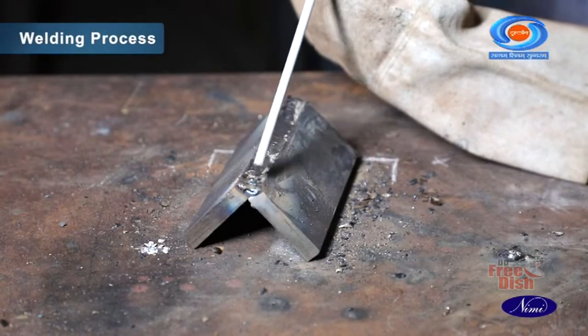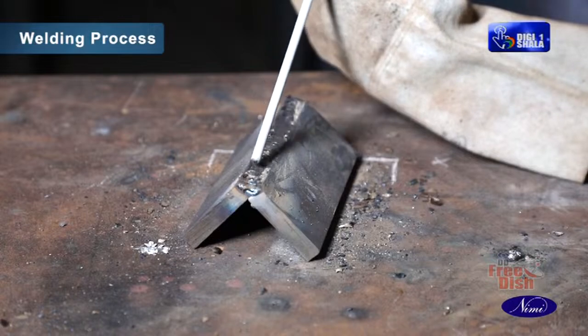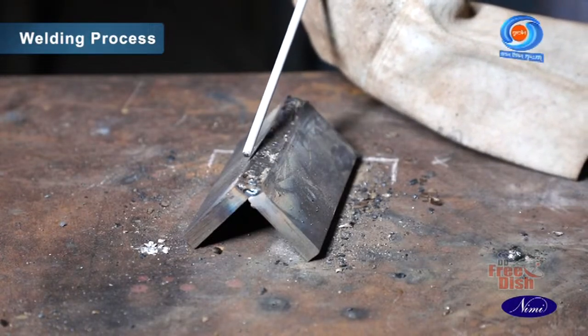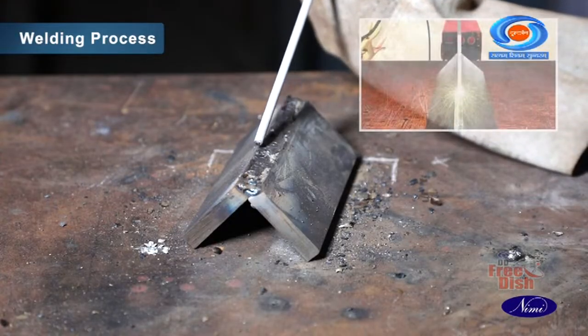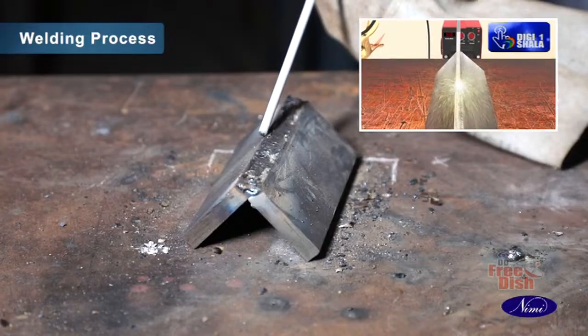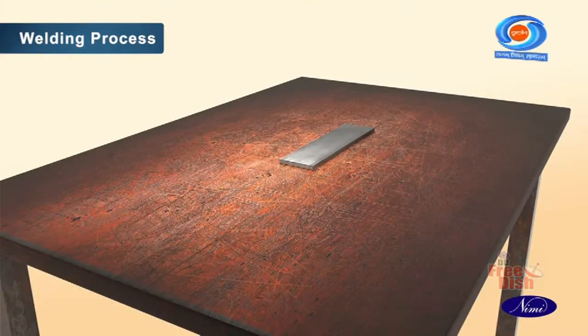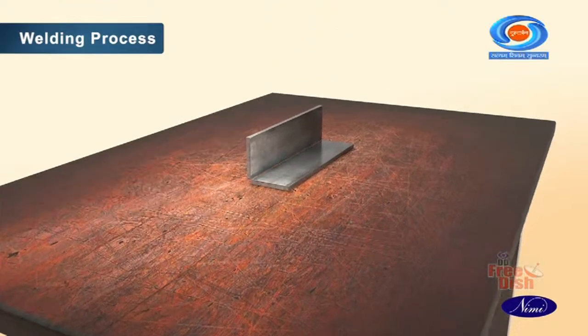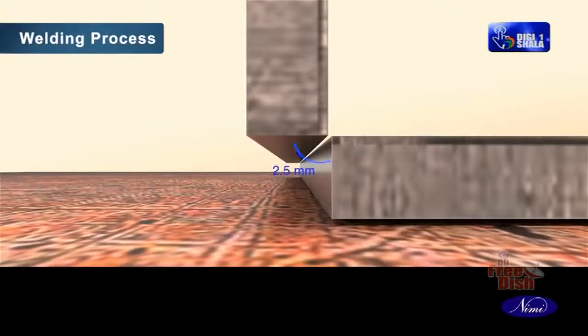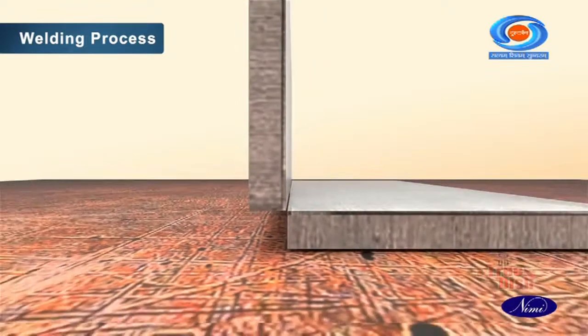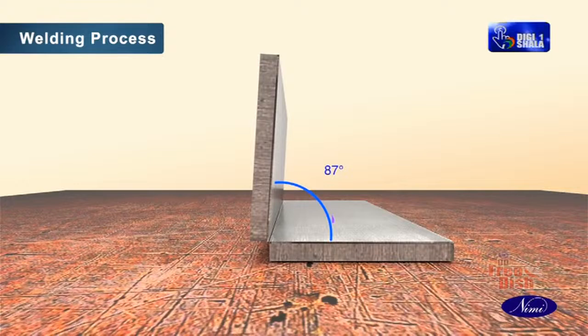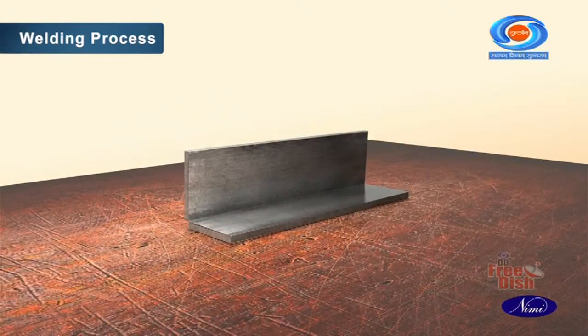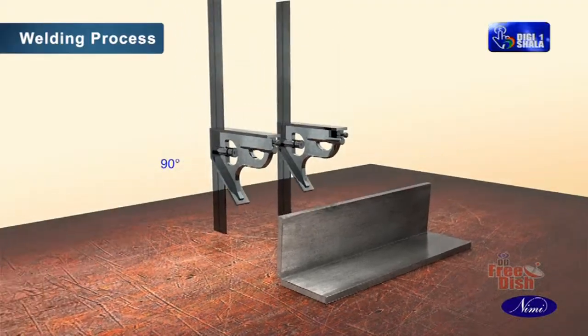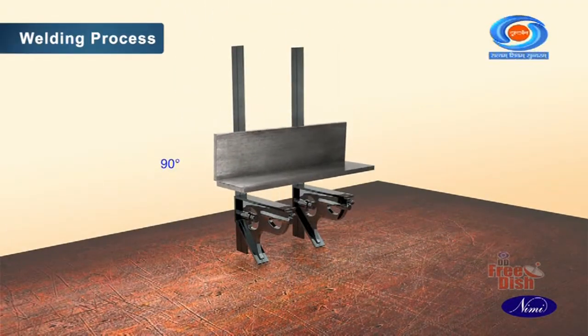Now, let us look at how to perform a corner joint weld on MS plate 10 mm thickness in flat position by SMAW process. Set the plates as an open corner joint on the table with parallel root gap of 2.5 mm throughout the joint. The angle between the plates is kept at 87 degrees to control the distortion. Another method to control distortion is to set the angle at 90 degrees and use a right angled iron fixture to minimize the distortion.